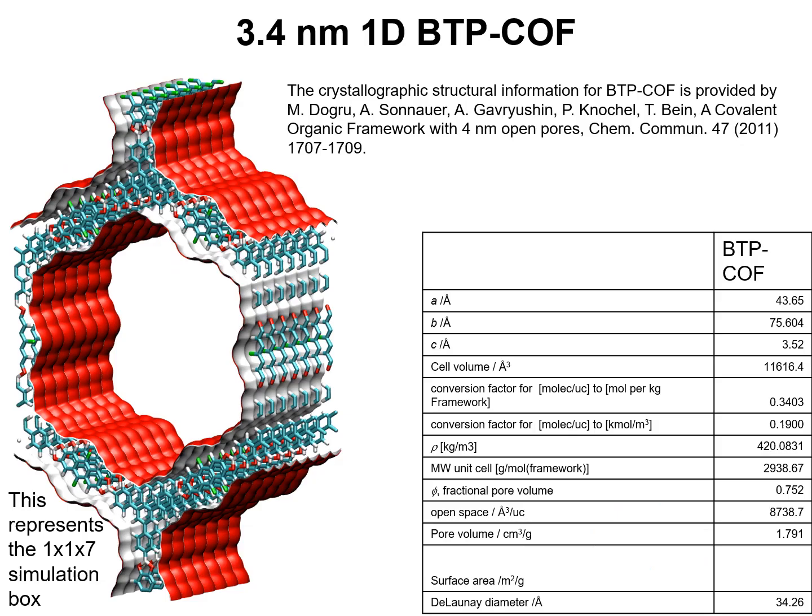Now let's have a look at pores which are larger than 2 nanometers, for which both molecule-wall collisions and molecule-molecule collisions are important. In this case, we perform MD simulations for a 3.4 nanometer covalent organic framework called BTP-COF. It has one-dimensional channels that are hexagonal in shape.